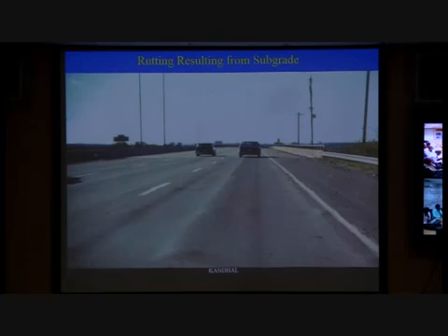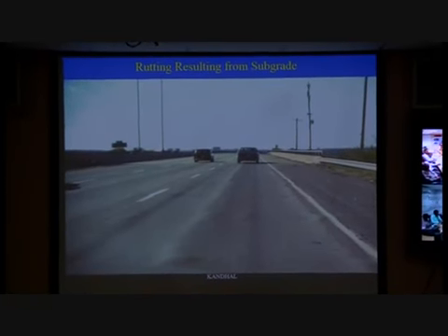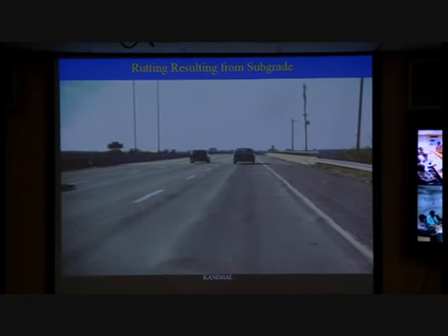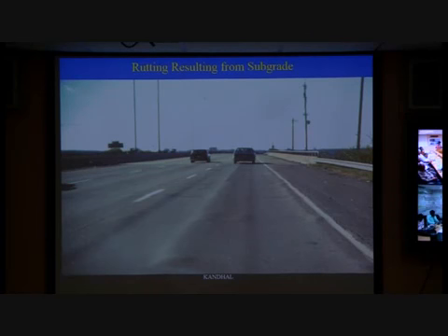So here you see a rutting. It's resulting from subgrade. The rutting can take place within the asphalt layer, or it can come from the subgrade. In this case, my guess would be, and I think the guess would be right here, that it's coming from the subgrade, because you see a bridge nearby. Mostly when we construct the bridge approaches, we don't do a good job of compaction of subgrade. Construction is not that good. So that's what happened here: the approaches were built last, after everything was finished, and most likely it was the subgrade.